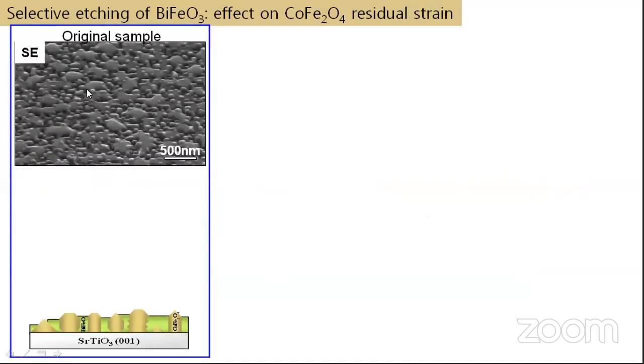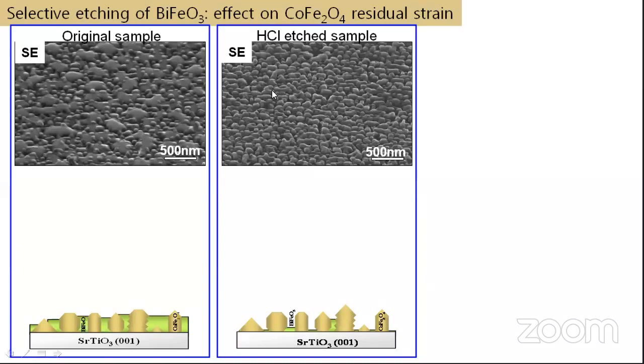So let us see, this is the SEM image of the original sample. You can see the matrix, and there is the cobalt ferrite here. The cartoon is something like this: you have a bismuth ferrite matrix with cobalt ferrite rods. After etching, you could clearly see that we have etched the bismuth ferrite part almost completely. You couldn't see any matrix part on this same scale, only the cobalt ferrite rods. These are the same samples. So that means we could etch the bismuth ferrite perovskite alone with different etchants.